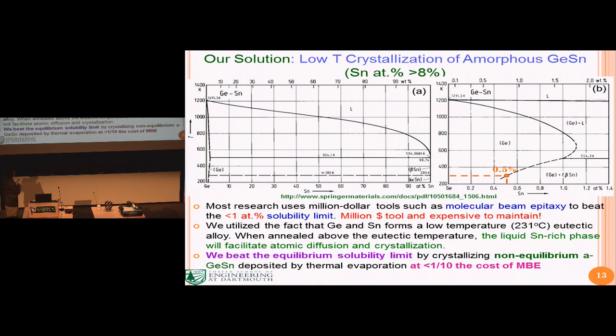So we are taking another look at this phase diagram from a more promising way. We're looking at this eutectic temperature transition here. Once you're above this low temperature, which is only 230 degrees or so, you have a solid phase of germanium tin in equilibrium with liquid tin. What that liquid tin offers is a much higher rate of atomic transport at low temperatures. So you can utilize that liquid phase to transport atoms such that it enhances the crystallization and the grain growth, as we'll show you in the next few slides.